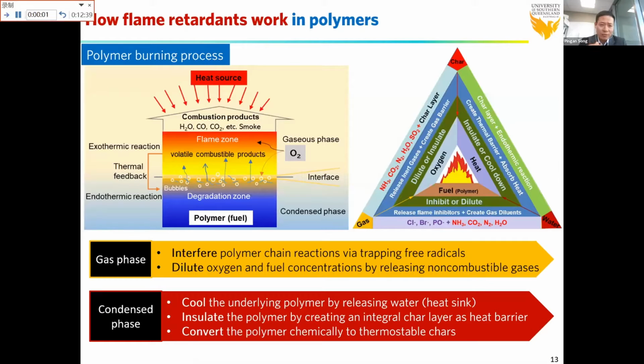Before we make fire retardant polymers, we need to understand how polymers burn and how the fire retardant works in a fire. In this scheme, you can see that at an elevated temperature, the polymer will thermally degrade to create small volatile combustible products as fuel to feed the flame. With oxygen, heat and fuel, the fire can be maintained until the polymer is totally burned. But if we want to stop the polymer fire, the flame retardant can play a role in the gas phase or condensed phase.